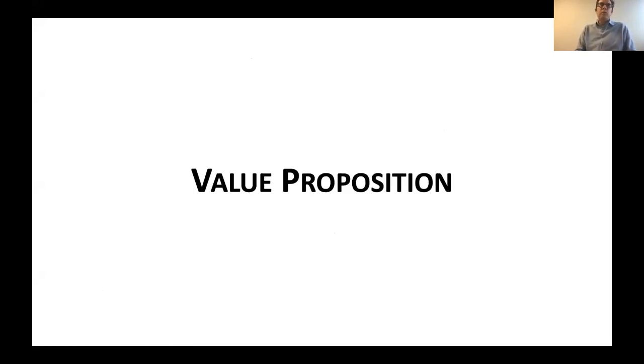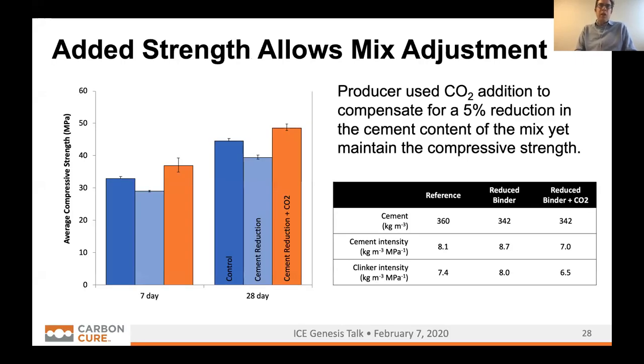So this comes to our value proposition. If you have stronger concrete, it allows you to reformulate your mix. So if we walk through this presentation, the producer has made 3 batches of concrete, and they've measured the strength at 7 and 28 days, which are typical benchmarks for concrete strength. On the left is the control batch with their business as usual mix, no CO2. And then they have taken out 5% of the cement, and the strength has gone down, which makes a lot of sense since the strength of the concrete cement matrix comes from the cement that you put in. Then if you take that cement reduced batch and add CO2, you actually get a strength benefit that allows you to compensate for the strength loss you had.